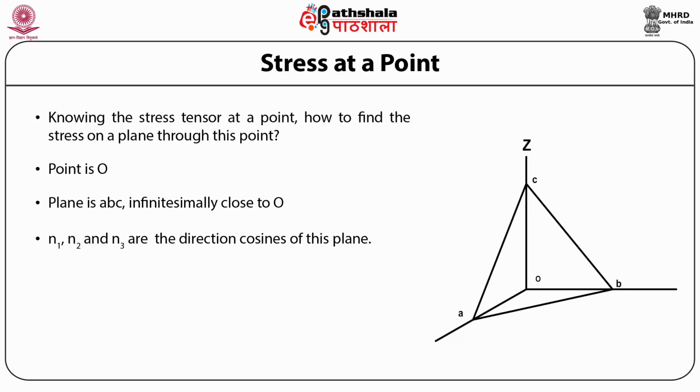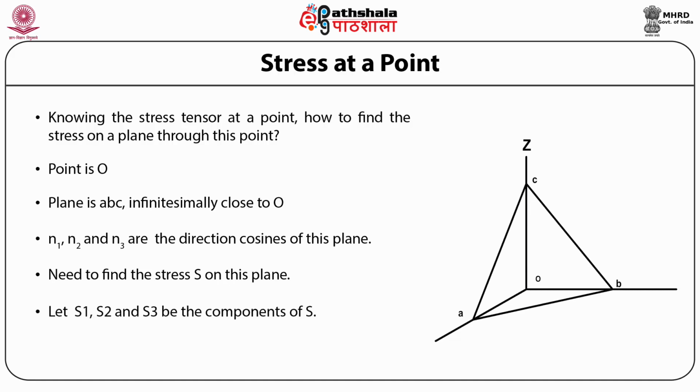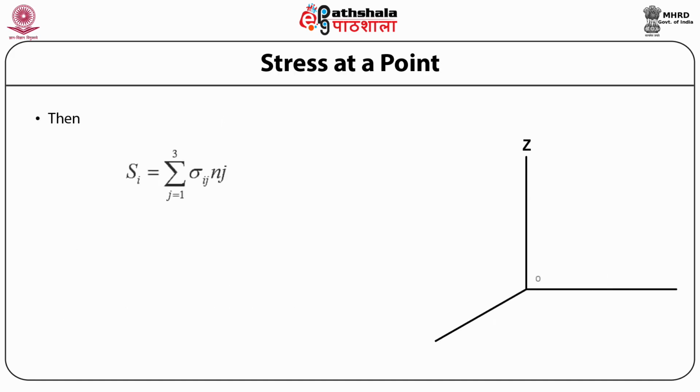Then it can be shown easily that the components of the stress on this plane are S1, S2 and S3, where Si equals the summation over j from 1 to 3 of sigma ij nj.